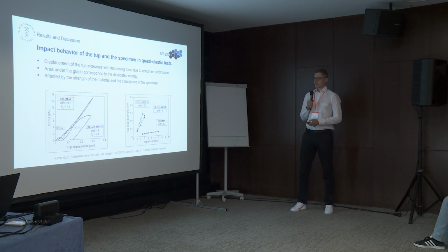Also, we repeated the tests for a different notch geometry, and we could see that the displacement of the tup increased with an increasing impact energy and depends on the material as well as the specimen geometry.